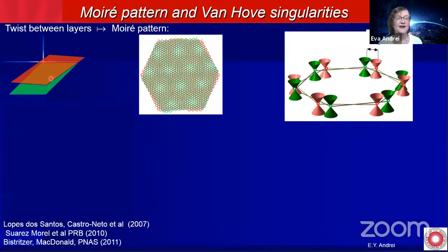So here we have a red graphene layer on top of a green graphene layer. We see the Moiré pattern that is formed. In the reciprocal space, you see the Dirac cones from the bottom layer, and I've plotted them all, although only 2 of them are inequivalent. So you see that they merge at some finite energy here.